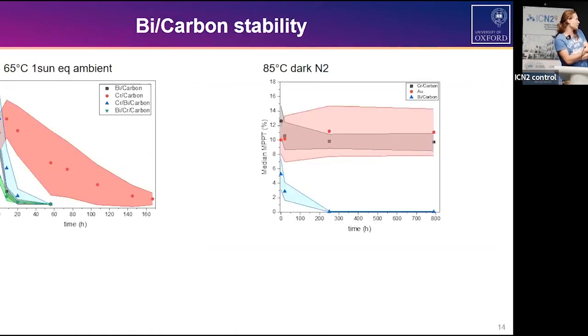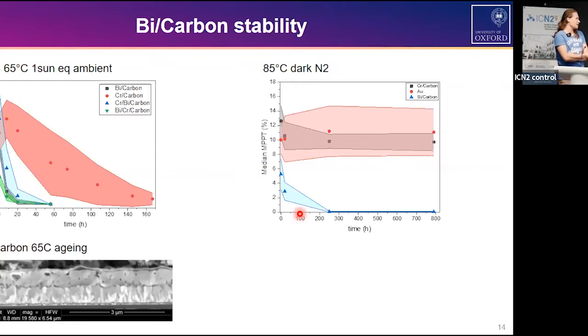And then we took the devices to aging studies, and they showed that the metal layer in combination with this kind of curing is not what we wanted. Especially the bismuth layer, one of the layers I tried: everything that contained bismuth was basically dying in 1 day. So I won't recommend anyone use bismuth and carbon in combination with perovskite. Even in a mild curing in nitrogen, under heat and dark, the bismuth devices were dying, and they behaved really strangely. The perovskite looked very damaged and amorphized.